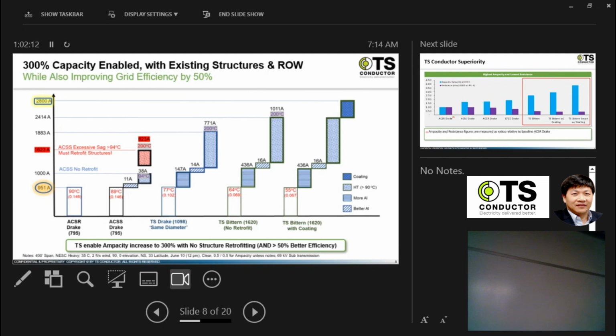And this is a line that has to be designed to accommodate what's called NESC heavy. It has wind loading and ice on the conductor as the worst design condition. You have to meet that requirement for the region. And so with the coatings, we're able to push the ampacity to be over 2800 amps compared to the baseline that was only 950 amps. That's where the 3x capacity comes in with TS technology.